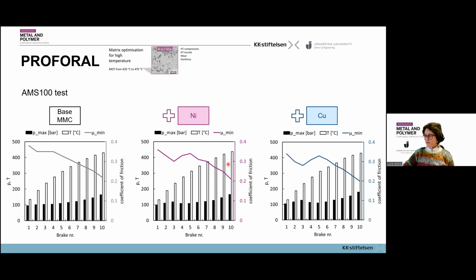In the case of the two experimental materials instead, as observed before, we have this earlier decrease in the coefficient of friction, but then it builds up again. So the tribo layer definitely has a different behavior with the new materials. And then there is a decrease towards 0.2 of friction at the end in all cases with the highest temperature. So here at brake number 5 is where there is the change of behavior. We reached the peak in the two experimental materials, while for the base material we were already in the descending area of the performance.